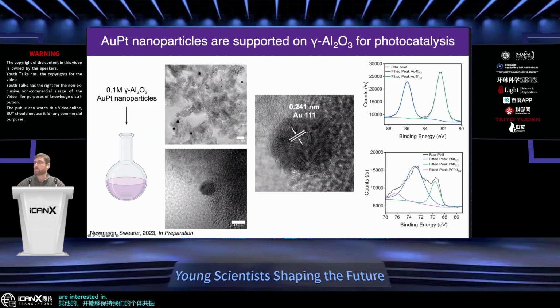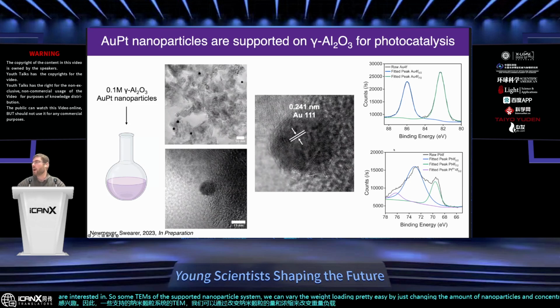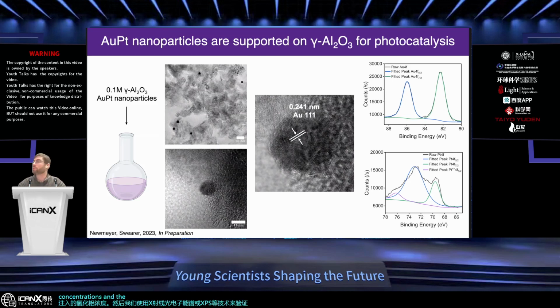So here are some TEMs of the supported nanoparticle system. We can vary the weight loading pretty easily by just changing the amount of nanoparticles and the concentration of gamma aluminum oxide that gets injected. And then we use techniques like X-ray photoelectron spectroscopy, or XPS, to verify the concentrations of gold and platinum within the system.